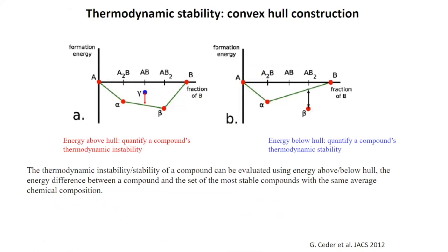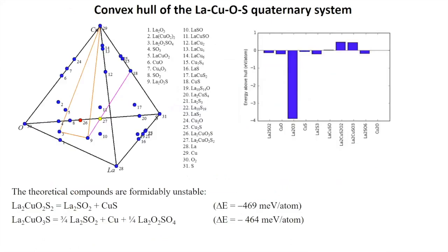So given that I'm out of time, I will just briefly tell you that Gabi and Chuck also looked at the convex hull of this quaternary system. There are 31 known elements and compounds that are involved. And essentially, what we find from this comparison is that, say by magic, we had been able to make this material where there were 2 apical oxygens replaced with sulfur. These calculations indicate that compound would break down into these 2 products and release an energy of 469 milli-electron-volts per atom. Okay, that is a lot of energy. And so essentially what that tells you is that this is incredibly unstable as a compound, and that it would instantly break down into these products.